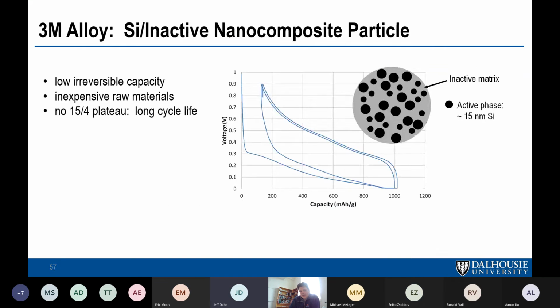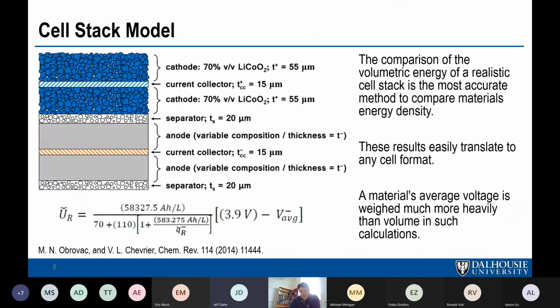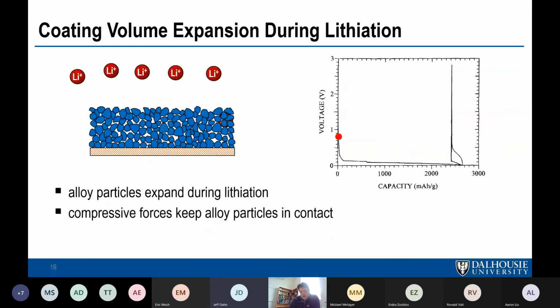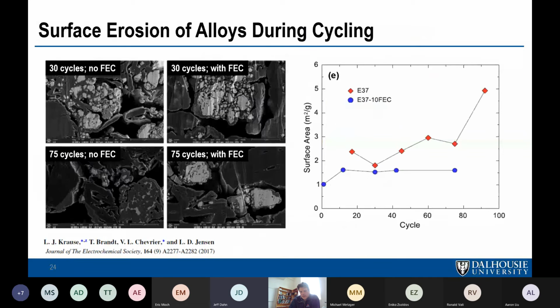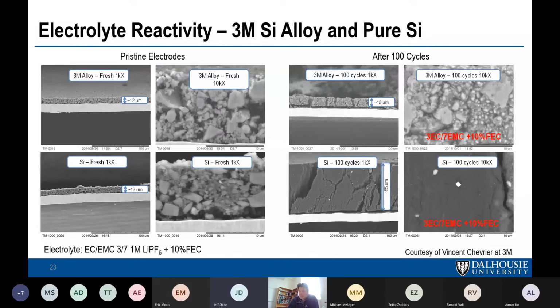And the reason I don't think anybody can answer your question is, I'll go back down here. Whenever you see papers about the composition of the SEI, they always include species that are the same for graphite, lithium carbonate. If you have FEC, there's lithium fluoride and things like that. But studies of the SEI on silicon also include species that include silicon. And the reason, I think, is because the surface is fracturing. And how are you going to study this and figure out whether there is any silicon in the SEI or not? The silicon is fracturing into such nano domains. Is there silicon in the SEI or is there not? I don't know. So that's the only difference that comes to my mind.